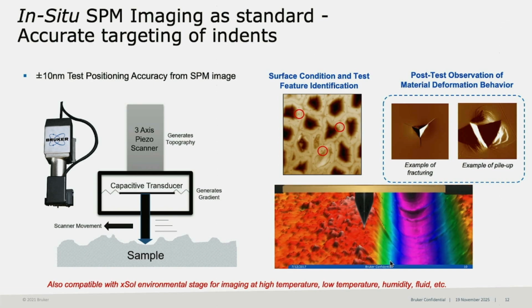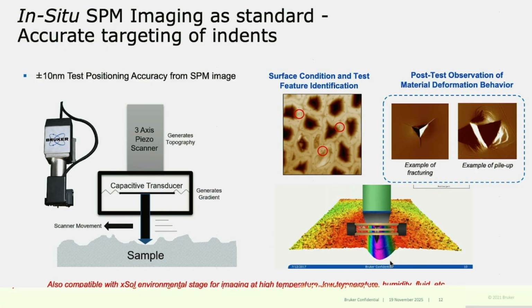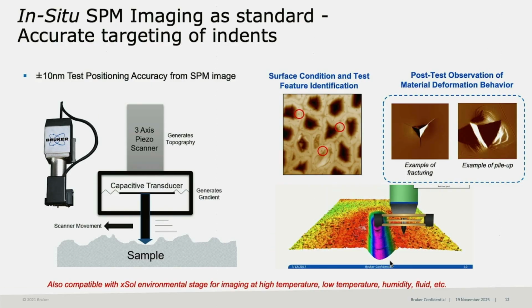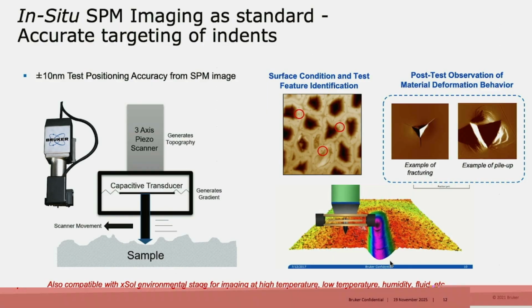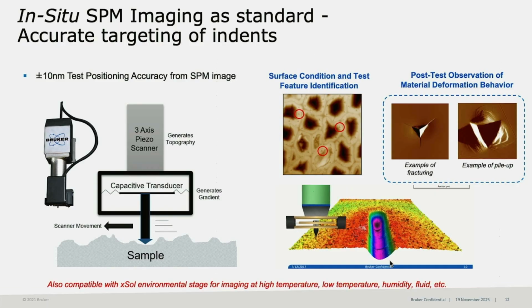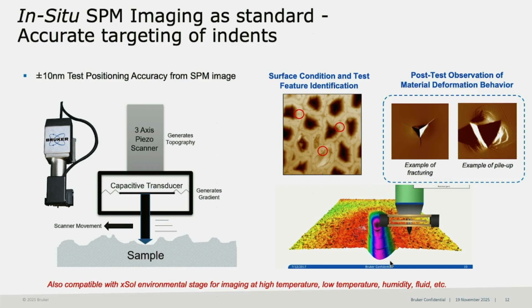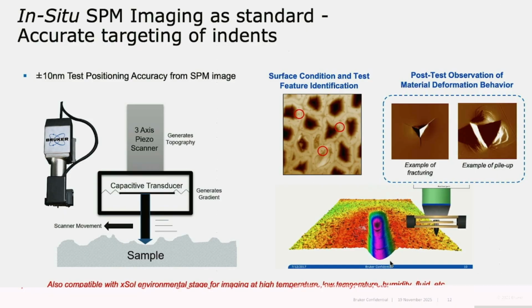How do we work? We use the nano indenter transducer here, and we adapt the transducer with the piezo scanner. The piezo scanner is like an AFM. They can just use the same probe to scan the surface. It will help you to understand the surface topography in the nano and the micro scale. So this you can scan. So this is the post indentation image. You can see the cracking here, right? So this just helps you to understand, even if you don't have SEM and TEM, you still can see the cracking.